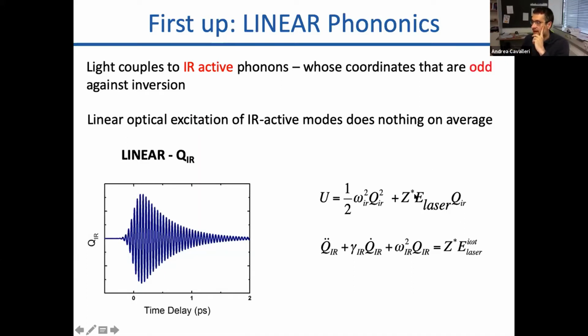And then it has a term that has to do with the interaction between the laser field and the charged phonon. So it's an electric field times a charge. So Z star is a tensor that tells me how much the charge of a single phonon is, times the coordinate. And from this, I can derive the equation of motion, which in this case is trivial, that of a damped harmonic oscillator. And this is why I see certain peaks with a certain width when I look at the reflected mid-infrared light or Terahertz light close to the resonance with the phonon.